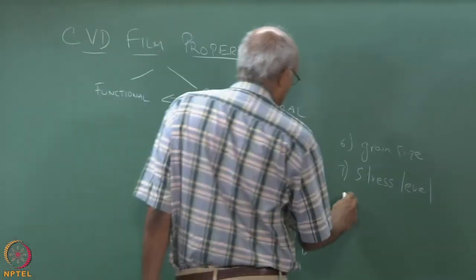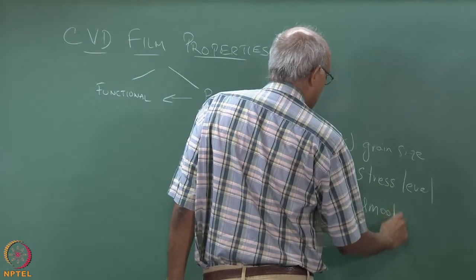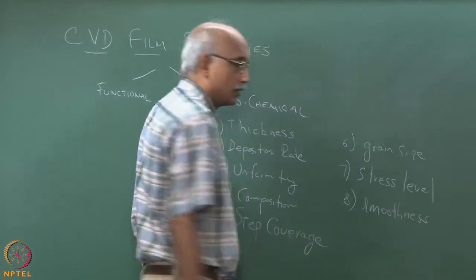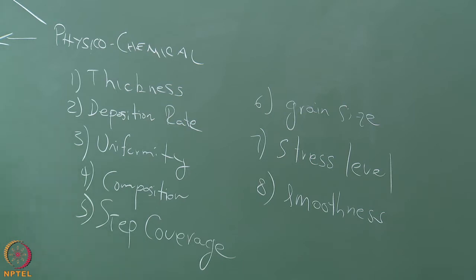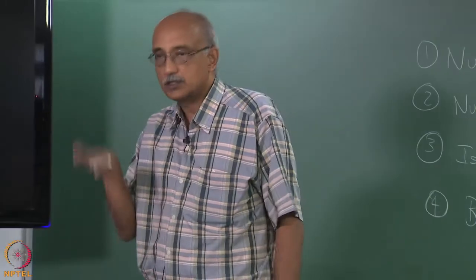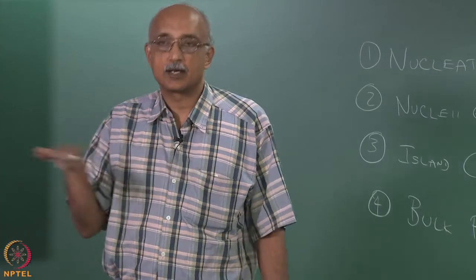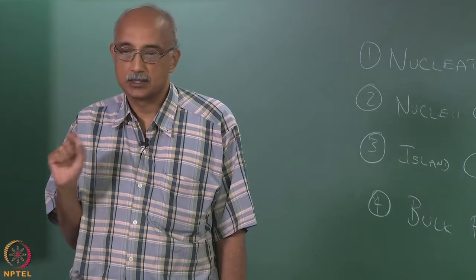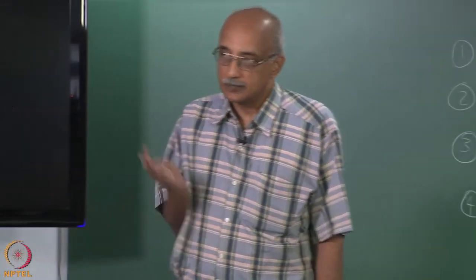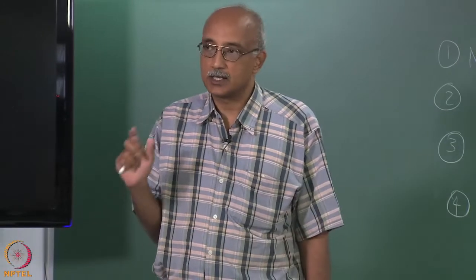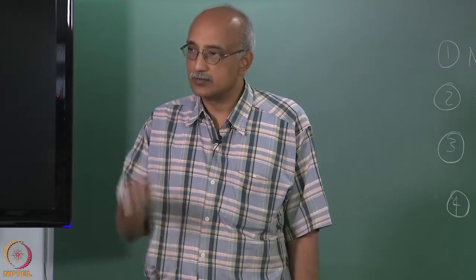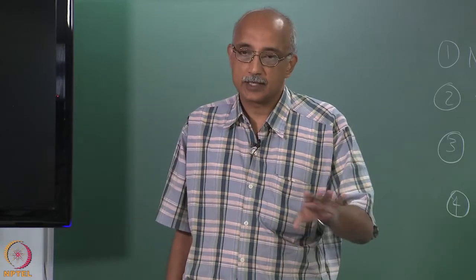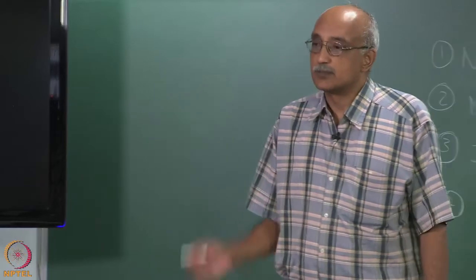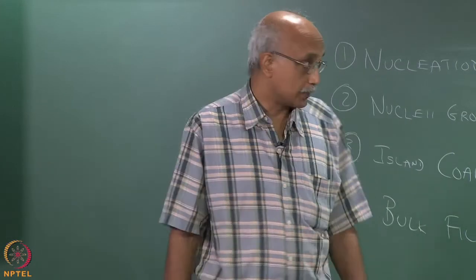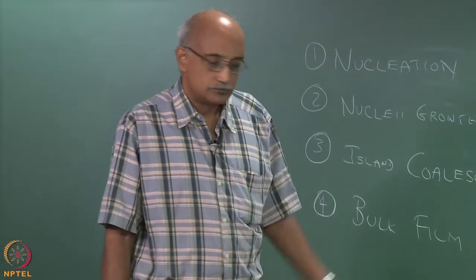Other things that may be of importance are smoothness or roughness of the film. When you do a morphology characterization in three dimensions, your requirement may be that the third dimension, which is a surface roughness profile, cannot exceed a certain value. You may have fairly tight standards on how smooth the film should be, in which case we have to use a technique like AFM to understand not only the two-dimensional structure but the three-dimensional structure of the film and ensure that the film roughness is below the specifications that we need for that particular product. What else? Obviously things like hardness, density,